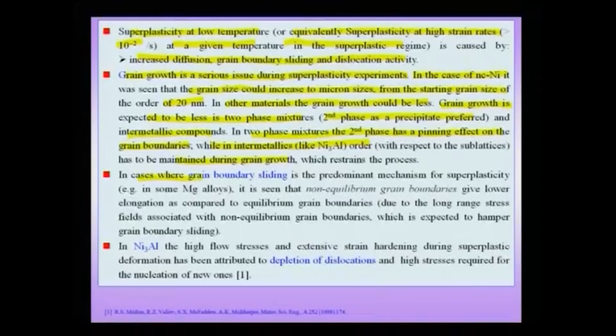In cases where grain boundary sliding is the predominant mechanism for superplasticity, and one example for that is typically magnesium based alloys, it is seen that non-equilibrium grain boundaries give a lower elongation as compared to equilibrium grain boundaries, and this is expected due to the long range stress fields associated with non-equilibrium grain boundaries, which are expected to hamper grain boundary sliding. So, this is an important effect wherein we are talking about two kinds of grain boundaries,